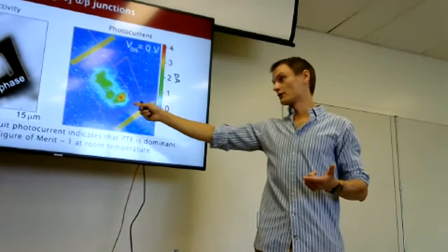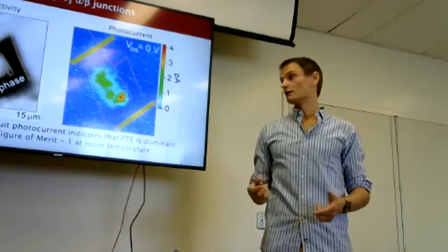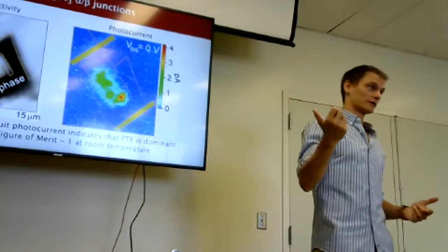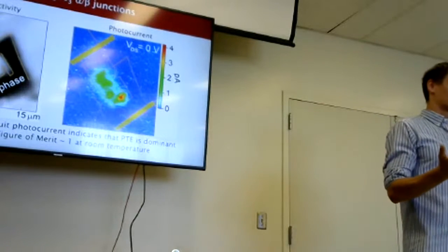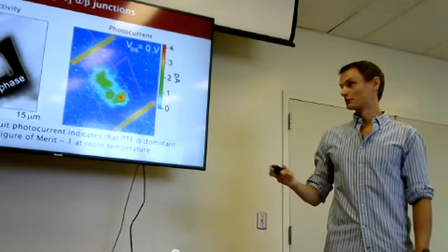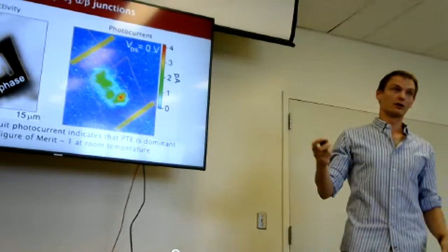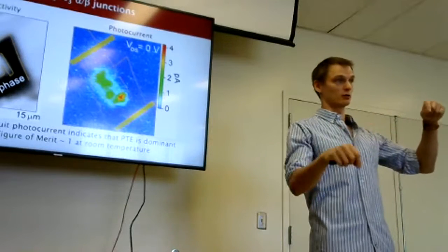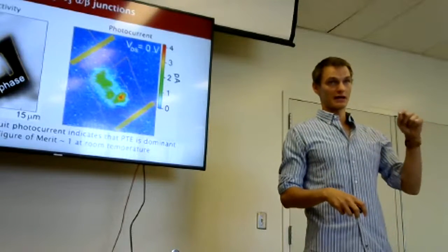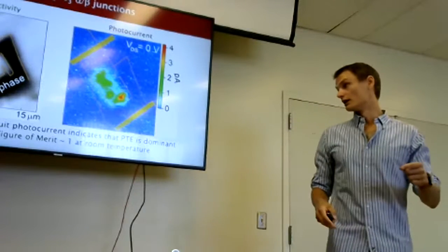What we see, interestingly, is that the short circuit photocurrent, so there's no bias applied anywhere, goes from beta to alpha, which is the opposite of what you would expect given the photovoltaic effect. And Xiaoming and Wang et al. showed that it was because of the photothermal effect, where you were heating the carriers and they were moving. So that effect overcame the photoelectric effect because they point in different directions.